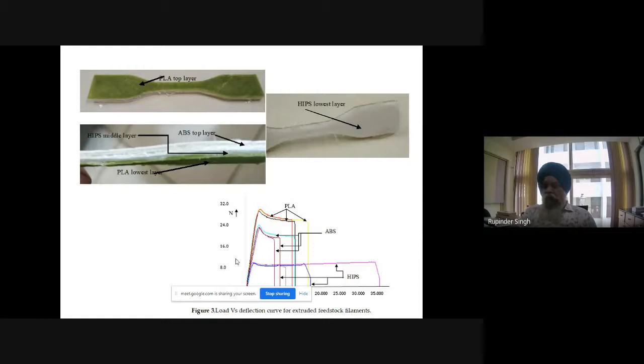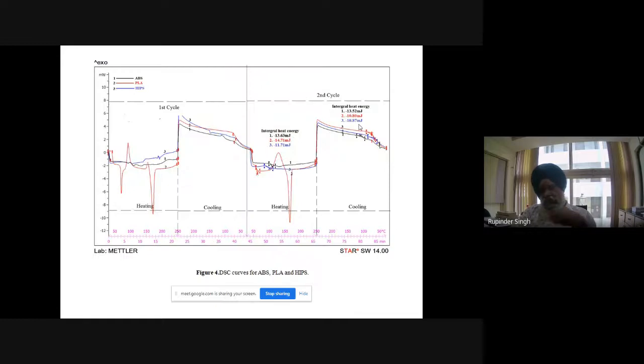Now this will be more clear from this picture. Here you can see the top layer of PLA, here the top layer of ABS, and here the top layer of HIPS was printed. We tried to see their stress strain curve. Like in the previous case, where we were trying to understand their thermal stability, here also we try to see how thermally stable this material is. In the second heating cycle, the ABS was taking input 13.63 and the output was 13.52.